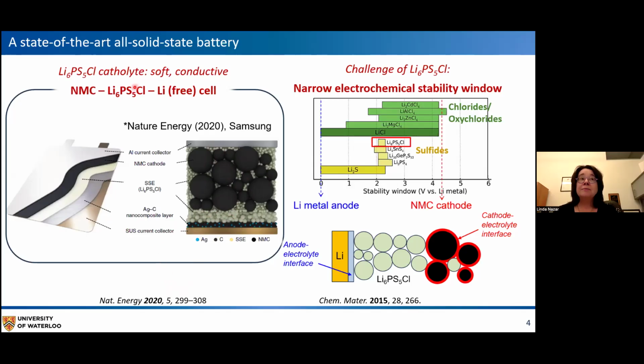But argyrodite has quite a few challenges, and one of them, in addition to many advantages, I should say, is that it has a fairly narrow electrochemical stability window, so it oxidizes at about 2.5 volts versus Li+/Li. And this means that such configurations need to have a coating on the cathode in order to inhibit that oxidation and stabilize that interface.